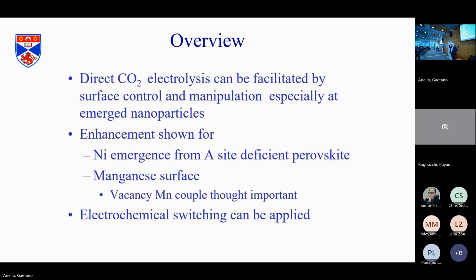So, to summarize here, we can do direct CO2 electrolysis. We can enhance this with nickel exsolution, and manganese is very useful. And we can apply electrochemical switching. Although if you've got a really good system and you apply electrochemical switching, it's worse. Just, again, the students get disappointed if it doesn't improve.